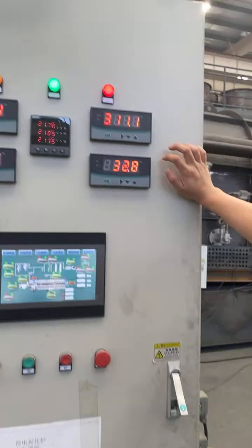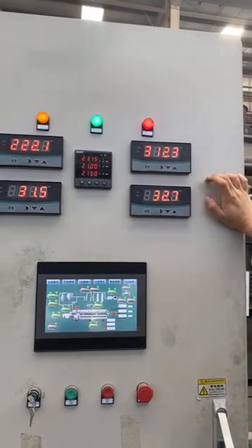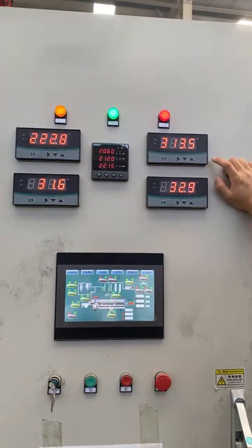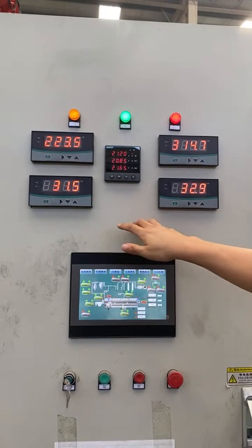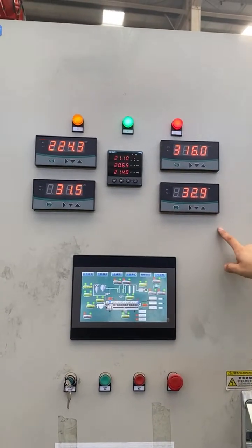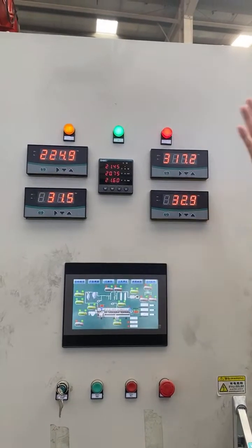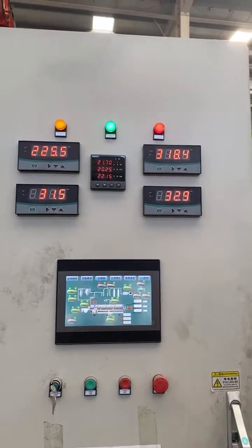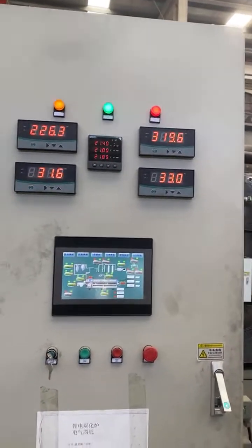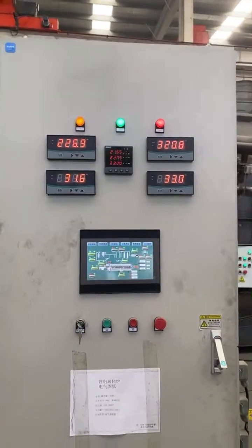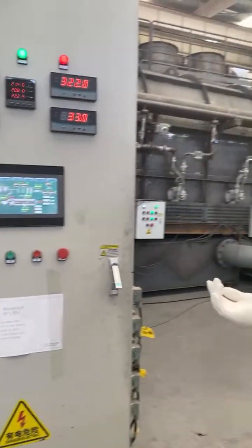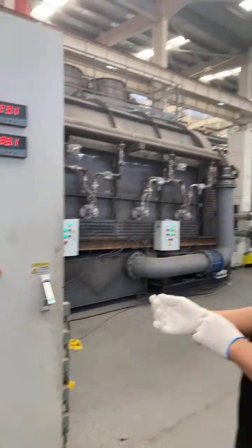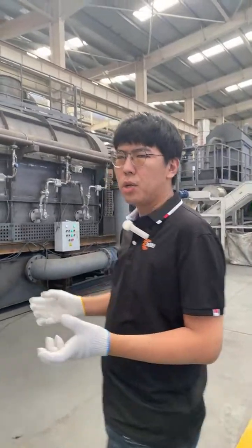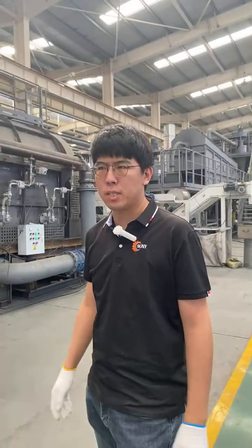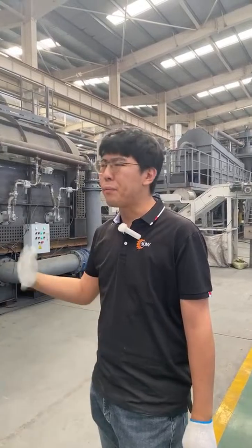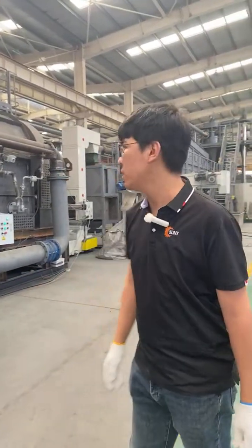And here we can see this is the temperature meter. We can see in the heat up part, the temperature already reached 300 degrees. But at the beginning and in the end, it is only 31 degrees. So we need to wait for this to heat up, and then we can do the recycling process. If you don't heat up your lithium battery, then during the recycling, the electrolyte will make material very wet. So the material will stick together. They will not be easy to separate. This is one problem. And after heating, this problem will be gone.